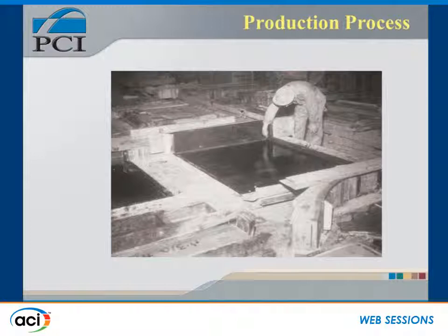Molds were typically constructed of wood, shellacked, and then lined with masonite, similar to what John Earley used. The masonite lining was given 2 coats of shellac, then coated with a solution consisting of 1/3 castor oil and 2/3 shellac. Shown here is a form for a 2-inch Mo-Sai slab with a 10-inch return. The workman is filling the joints of the form with molding plaster to prevent leaks.